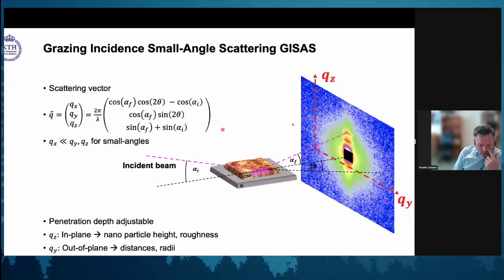So in looking at this, I will talk about two things. Grazing incidence is trying to use the full field or the full detector image by having an incident beam. In this case, I formulated also grazing incident scattering. You can do it with neutrons, and you can do it with X-rays. What you will get in grazing incidence is a detector image, and you can use both the lateral and the vertical information to characterize the structure you have in the film. And we can actually adjust penetration depth, and by looking at this sort of behavior, we can look at nanoparticle heights, roughness, or distances and radius of structure. And we'll get back to that throughout the presentation.